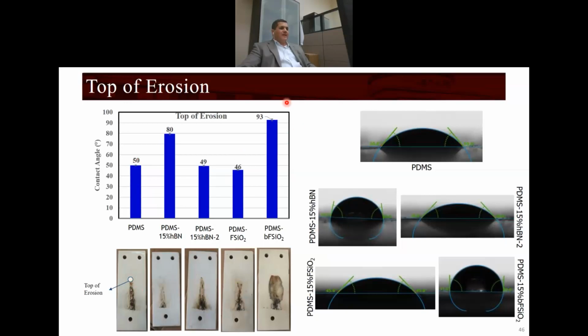The biggest difference is why I mentioned earlier that the ball milled fumed silica is acting much better, because it is still maintaining its hydrophobicity after the erosion. You see the fumed silica without milling dropped a lot after exposure to 4.5 kilovolt. Same thing for this sample. We need to see what's happening on this. We need to repeat these two because these are supposed to be the same sample. But if you ignore what's happening here, the PDMS is the same too. It does not maintain its hydrophobicity after erosion.